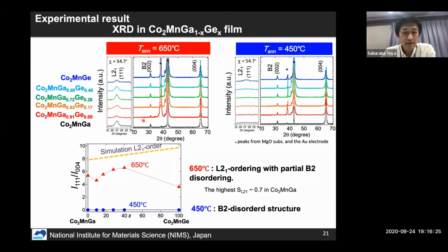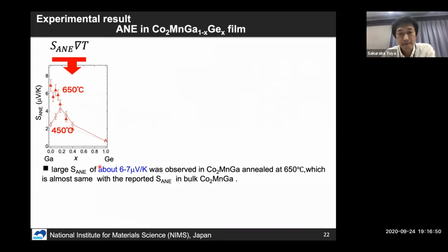So as I summarized in this figure, at 450 degrees C, we could not see the L21 ordering in any gallium germanium composition ratio. But when we increase the annealing temperature up to 650 degrees C, we can obtain a higher L21 ordered state in every sample.